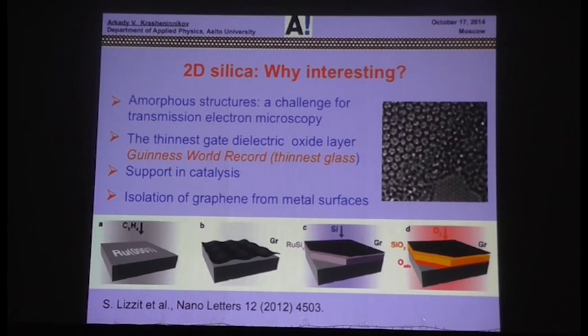Besides, there's another paper coming from Silvano Lizzit's group. We're not involved in this work. They managed to intercalate silica between graphene and metal after growth. So essentially, this way you can isolate graphene from metal, at least electrically, without an expensive transfer process. And also, you frequently create defects in graphene when you transfer it from a metal substrate to polymers. And I believe that in our experiments our coworkers did pretty much the same thing when they tried to grow graphene on copper. As I mentioned already, silica Si and O atoms ran from the quartz tube and were intercalated between graphene and metal.